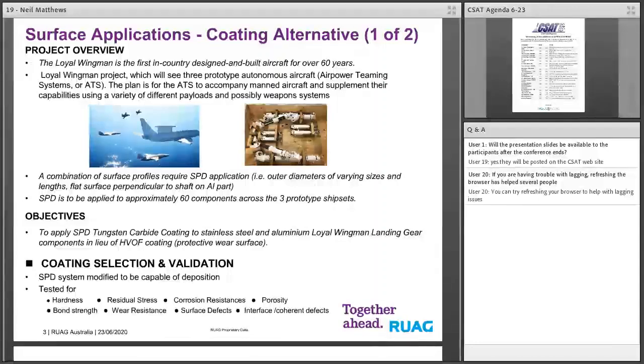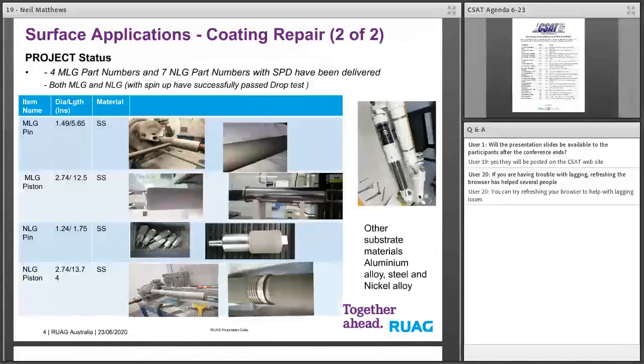The objective was to see if we could actually come up with a coating on stainless steels, and there's some aluminium alloy items as well, in lieu of existing coatings, that's both hard chrome and HVOF. So we've had to modify our system for the deposition. We've also modified powder types, so we've selected and generated a particular powder type, put it through all forms of testing, and we've had some success. Next slide, please.